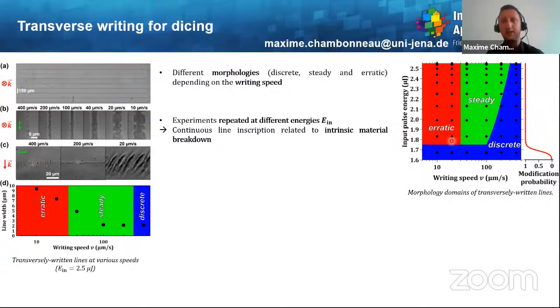One can see that it is possible to write continuous lines transversely only when the modification probability is equal to 100%. This means that transverse line inscription inside silicon is intimately correlated with intrinsic breakdown and intrinsic damage production inside the material.